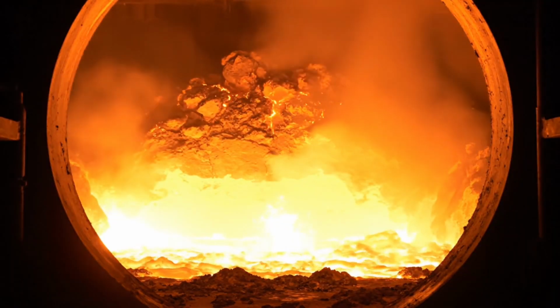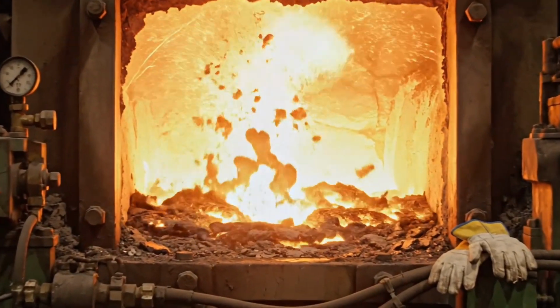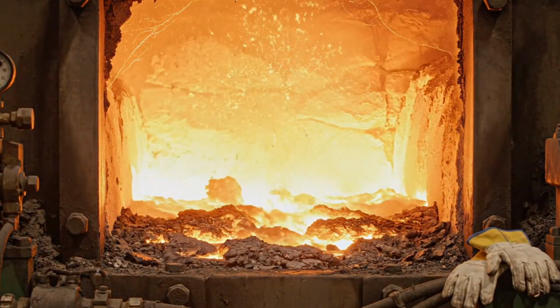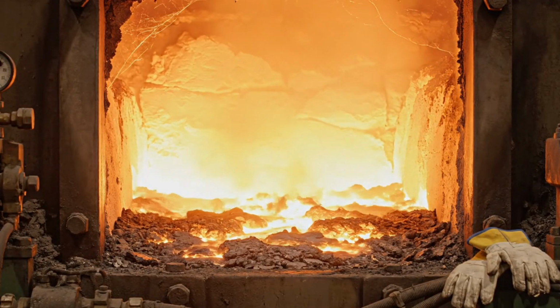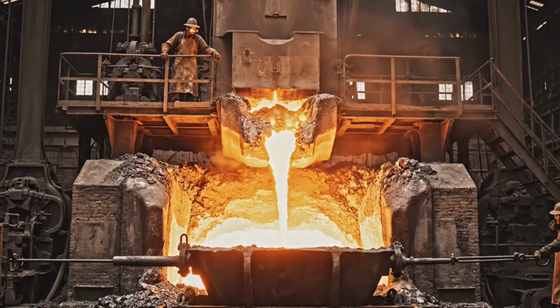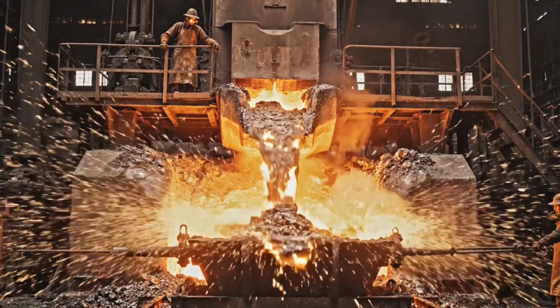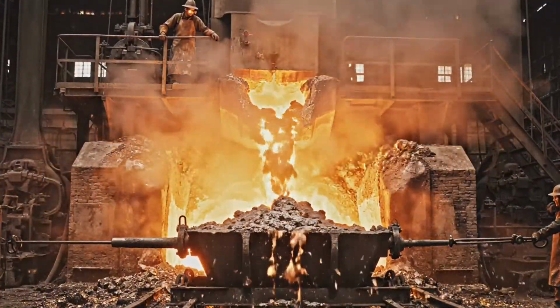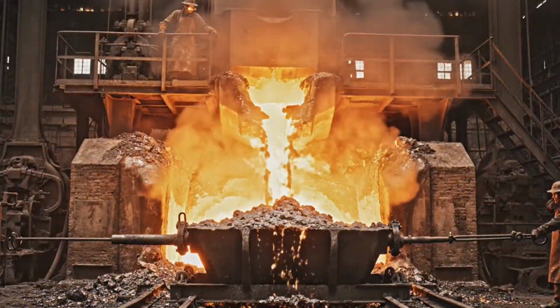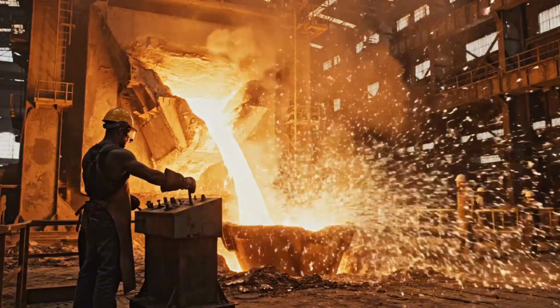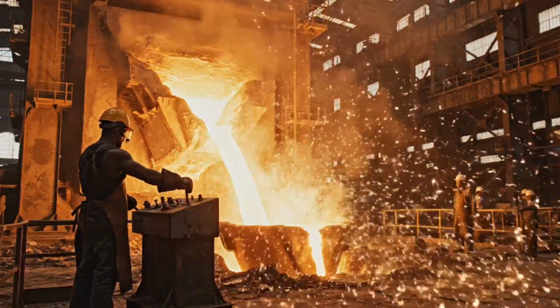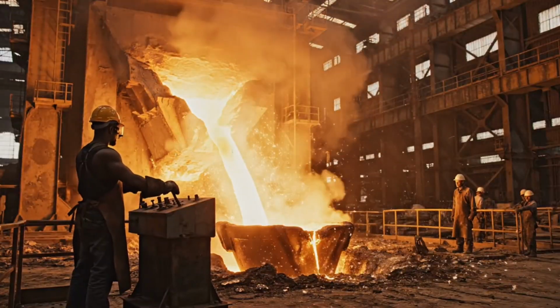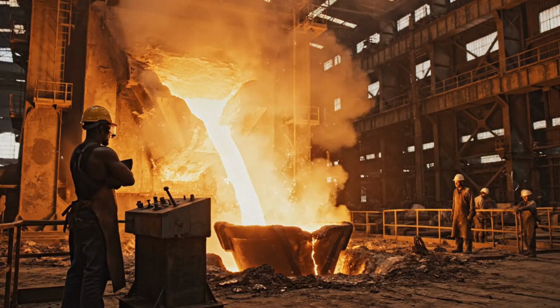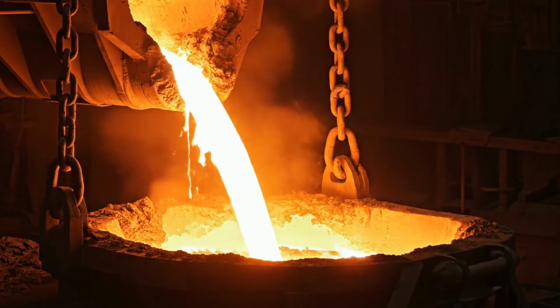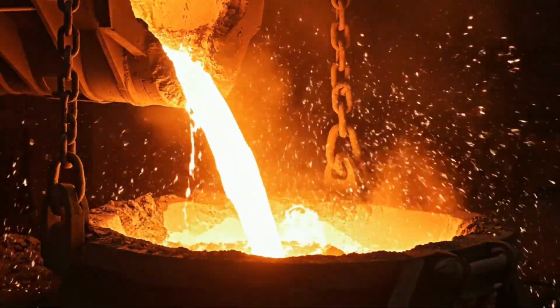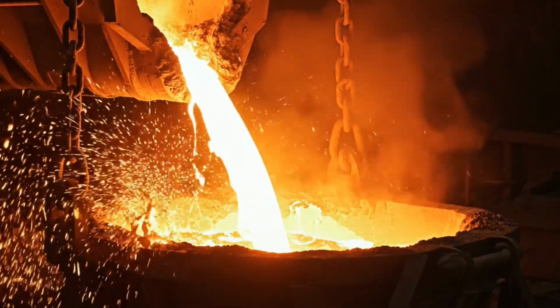Inside these towering structures, temperatures reached 2,500 degrees Fahrenheit as preheated air, or sometimes pure oxygen, was forced through the mixture from below. The limestone combined with impurities to form slag, which floated to the top and was drawn off, while the iron, now molten and called pig iron, was tapped from the bottom in glowing orange streams that filled vast ladles. But pig iron was too brittle and contained too much carbon to serve as armor plate.